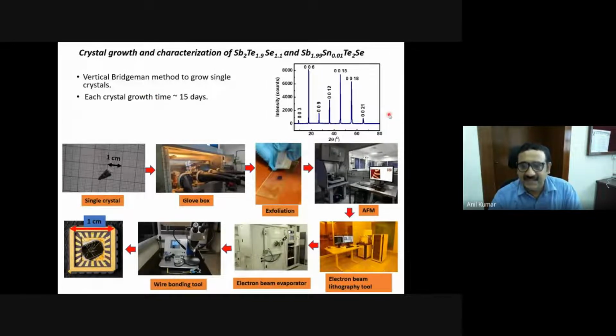Typically, a student takes around 15 to 20 crystals to get his final 4 or 5 good crystals. 15 to 20 crystals means 20 into 15, almost 300 days. He or she will be doing the crystal growth without any break, and that's not counting all the characterization, etc. So people put in sufficient effort to get to that stage.